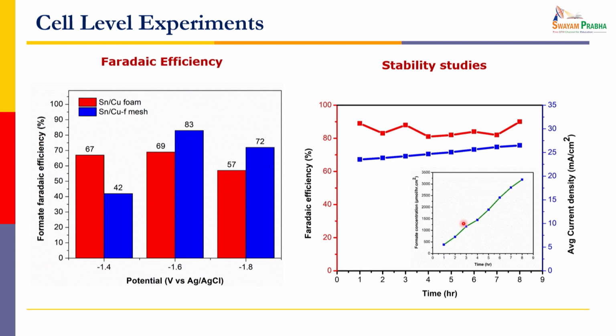We also looked at the stability, how long it can work without changing its performance, and you can see that close to 8 hours the same Faradaic efficiency is maintained. So the catalyst is stable for this duration in some initial experiments. Later we increased the hours. So it's stable, it has a high surface area, and it has 83% selectivity towards formic acid. That's the kind of results we have got from here.